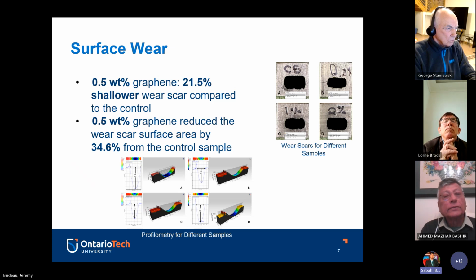And you can also see, while the profilometry images are not as clear as the other ones because of scale, and of course you guys are a little far away, we can actually see that reduction as well. So it's clear that the graphene-enhanced grease was making a difference. However, we still needed to run some more tests in order to prove that it actually makes a full difference. And this is where we had to get to standardized testing.